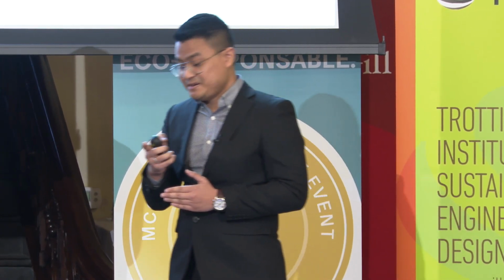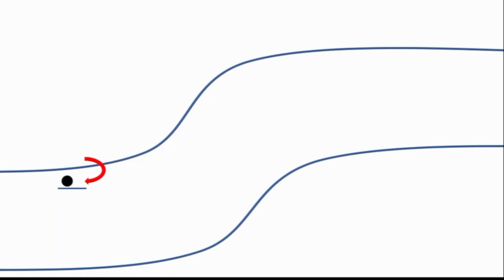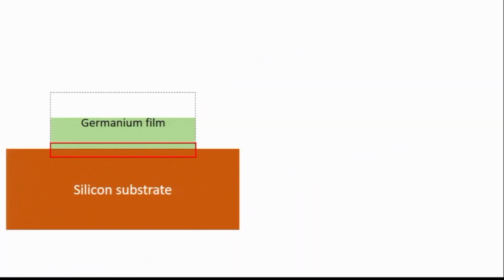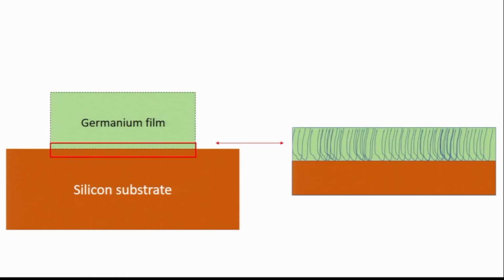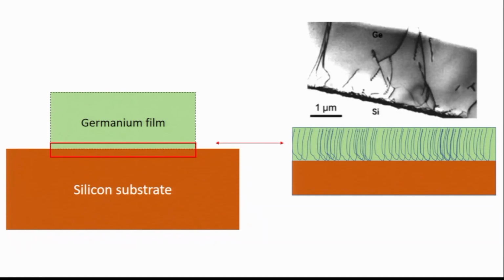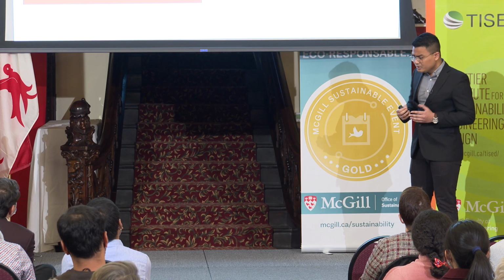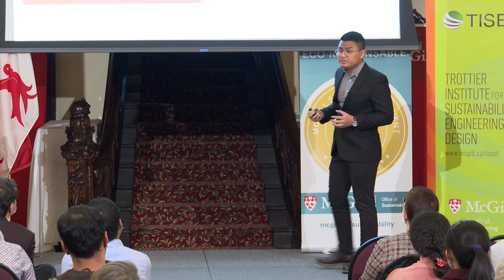The problem is when we grow germanium on silicon, which commonly occurs in the vertical direction, atomic imperfections are generated that look like bunches of half loops inside the germanium layer. And this, you see, happens because of the lattice mismatch between germanium and silicon. These half loops look like the following in an electron microscope. And we have seen how these imperfections will degrade the performance of our detector. So this is a really challenging problem in the community.